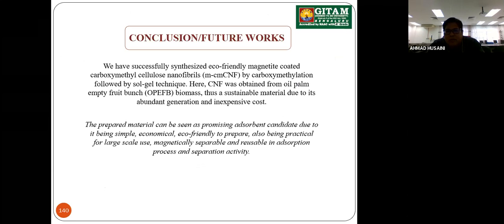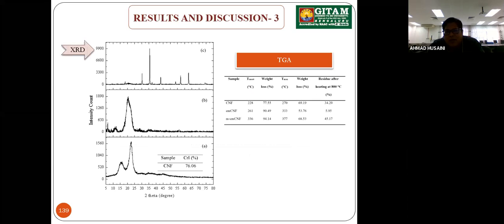And lastly, from the TGA, it was observed that the thermal stability increased for the magnetite cellulose nanofibrils, showing that the compound has high thermal stability, with the residue at 800 degrees more than 45%. Next.